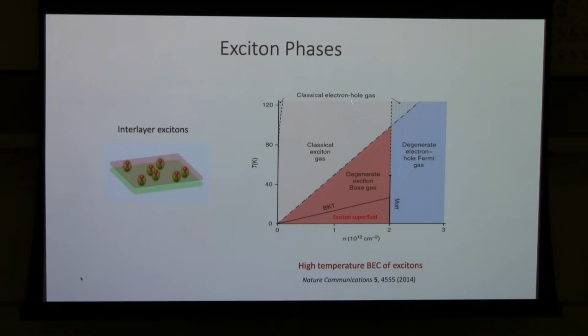And then if you lower the temperature, the de Broglie wavelength of the thermal excitons becomes longer and longer. Sooner or later, it can be larger than the separation of the excitons, so we can reach a degenerate boson gas. And if you lower the temperature further, one should be able to reach an exciton condensate that can live at tens of Kelvin or maybe even higher. Compared with atoms, because the exciton mass is much, much smaller and the exciton density we can realize is much, much higher, you don't need to go to nanokelvin to get the Bose-Einstein condensate. You can get it at tens of Kelvin. So at least that's the hope.